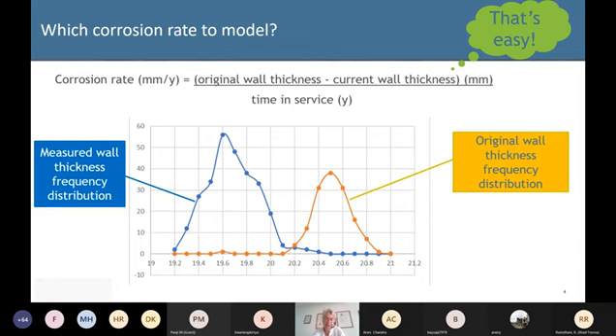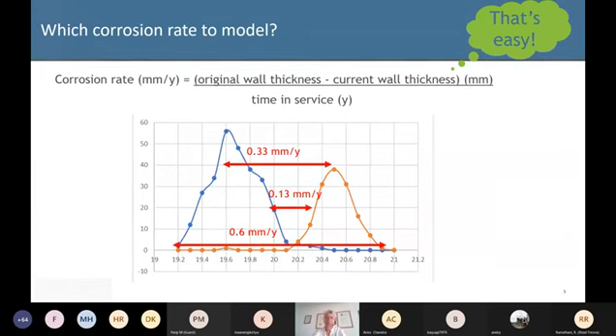We've got similar data for a number of locations, and it's basically just inspection data, but it's probably more detailed than we normally get hold of, because it was very strictly taken every few millimeters around the pipe. They took wall thickness readings with ultrasonic inspection, so it's pretty accurate. And even so, what we see is that there's a broadening of the variation of the width, and there's quite some question mark about, well, actually, what represents the real thickness of this pipe? So if you think about it, the difference between the original wall thickness and the current wall thickness could be almost any number you choose, depending what number you pick for your original wall and what number you pick